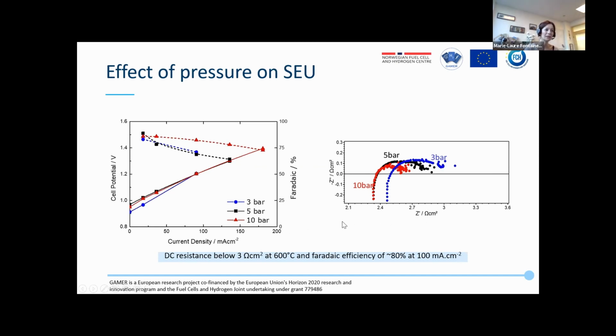And to understand what is happening, we have also done impedance analysis, and you can see that both the ohmic resistance and the electrode contribution are actually improved by increasing the pressure. When we compare this with the knowledge that we have generated on the material, this is ascribed to both better hydration properties of the material when we increase the pressure, with more protons getting into the proton conducting material, but also enhanced kinetics at the electrodes.